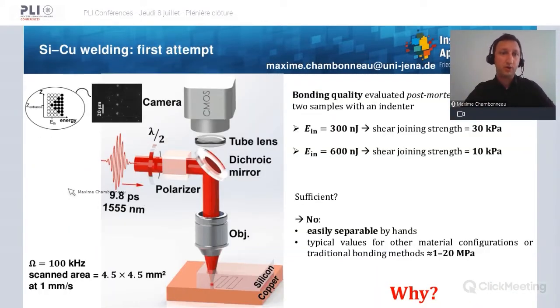To do so, we will employ essentially the same setup, except that we now work around 10 picosecond pulse duration. We illustrate semiconductor to metal ultrafast laser welding with silicon and copper. We have a macroscope for positioning, for knowing the relative position of the focus with respect to the entrance surface of the silicon sample. After welding with those conditions, we evaluated the bonding quality post-mortem by separating the two samples with an indenter.